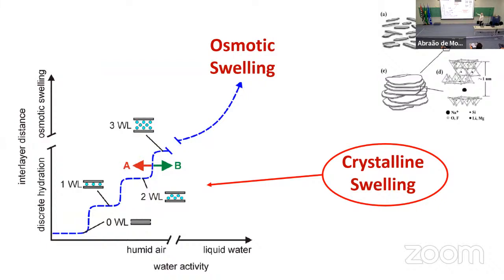If you take this system of decks of cards and expose it to water, it swells. I mean, there are some clays that swell and some that do not swell. In this talk, I will talk about the ones that swell. We distinguish between crystalline swelling and osmotic swelling. When you start with the dry system, say clay powder, where the grains in the powder are these decks of cards, and expose it to humid air, you will get intercalation of water into the system, layer by layer, until you reach three layers. Then if you expose it to liquid water, you get into the osmotic swelling regime where the cards separate completely.